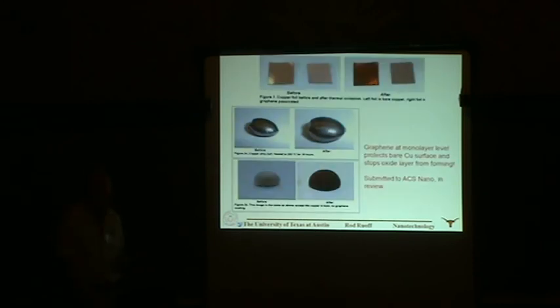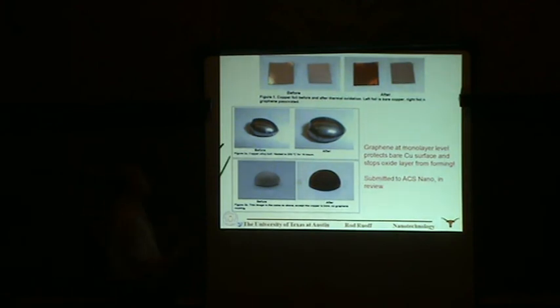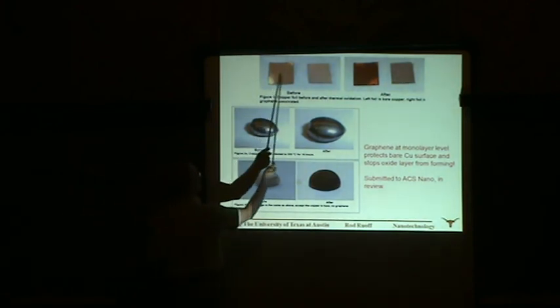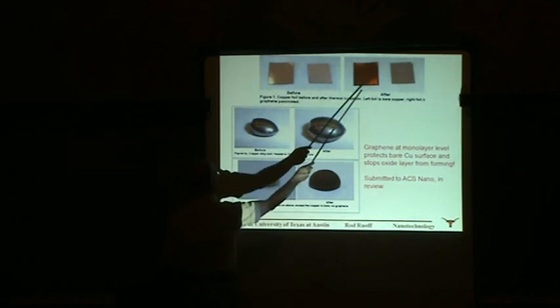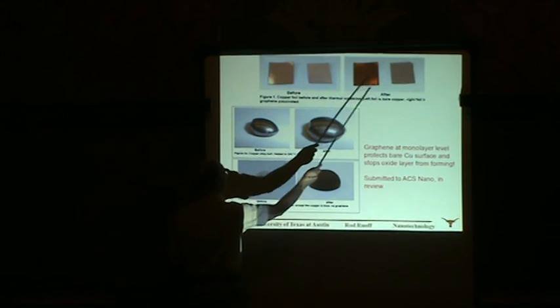And I won't bore you with all of the analytic techniques that we use, other than to say that just to the eye, you can see examples before and after. This is unprotected, it tarnishes noticeably on exposure to 200 degrees Celsius in the air, but when graphene is coated on it, we see no evidence of tarnishing, for example. And we use techniques like X-ray photoelectron spectroscopy to show that the graphene-coated regions always remain as neat metal that didn't form the oxide, whereas the regions that were not coated formed a clear presence of copper oxides.